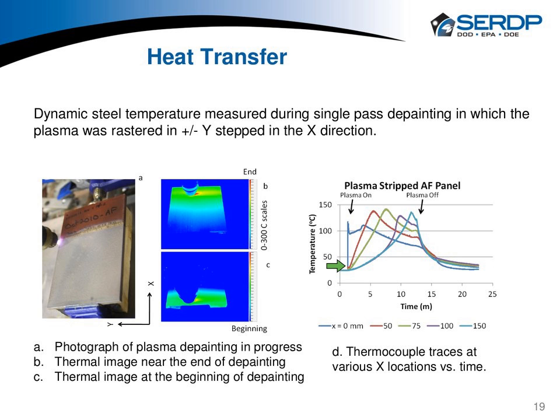And notice that at each one, the temperature will build, it will maximize, and then it will drop. Clearly, as the plasma rasters over the surface, there's heat input, but then it readily moves off. And so there's essentially a heat wave that moves through the surface. Notice that the temperature really never gets much hotter than, we use 200 C as our absolute top temperature, which is roughly 400 F, well below annealing temperatures of steel in this case. So we're designing our system specifically for this type of substrate, which is different from aluminum or composites, okay?